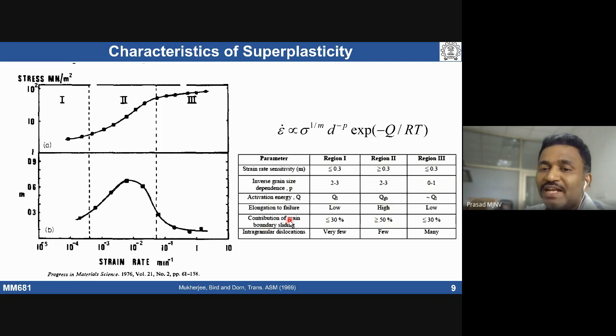Grain boundary sliding is going to take place at all strain rates at elevated temperatures. However, its contribution will be maximum. Grain boundary sliding contribution will be maximum in region 2, as compared to region 1 and region 3.